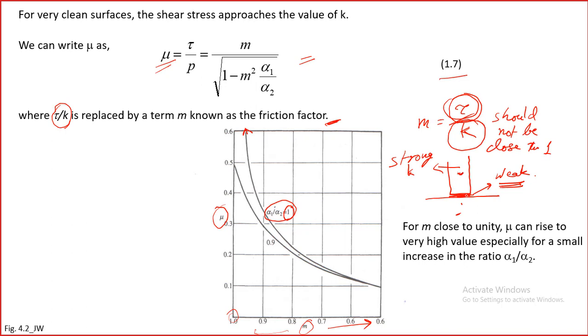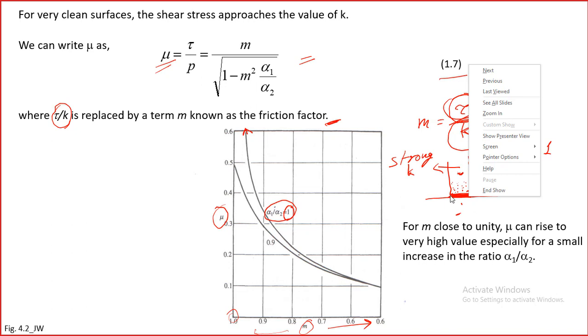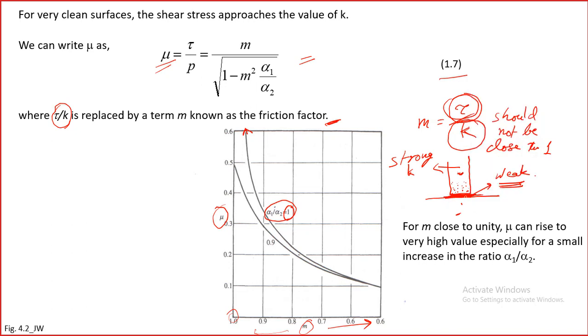Often what happens is we can keep it weak by introducing something here, and sometimes we add some solid lubricant in the material, a solid lubricant which should not affect the strength of this material. Since the solid lubricant will be present at this interface, it will reduce the shear stress of the interface. In some way you can also say it is like lubricating the surface, which is true. It is basically lubricating the surface using a solid lubricant while keeping the strength of these two materials high. And this has been found experimentally to be true. So this is one way to solve the friction problem.